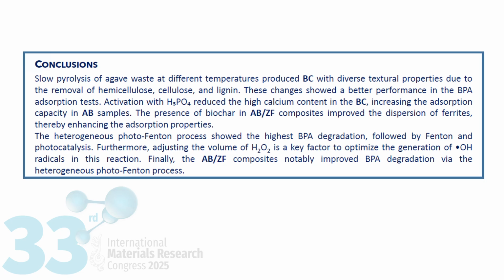The presence of biochar in AB/ZF composites improved the dispersion of ferrite, thereby enhancing the adsorption properties. The heterogeneous Photo-Fenton process showed the highest BPA degradation, followed by Fenton and photocatalysis. Furthermore, adjusting the volume of hydrogen peroxide is a key factor to optimize the generation of hydroxyl radicals in this reaction. Finally, the AB/ZF composites notably improve BPA degradation via the heterogeneous Photo-Fenton process.